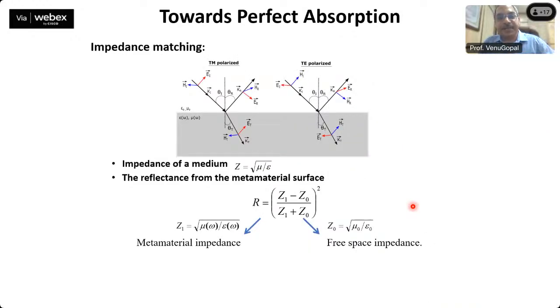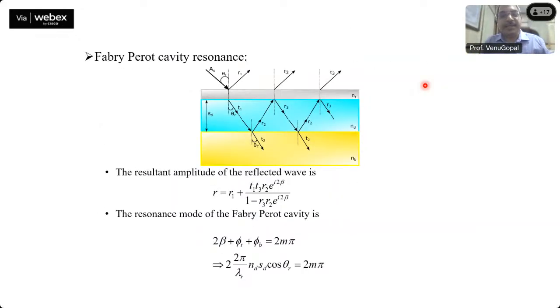I'll show one example of a perfect absorber. For different applications, sometimes we need 100% of the light to be absorbed within a few nanometer thick active or lossy absorbing material. For example, it can be 10 nanometer silicon, or 3-4 nanometer silicon, or germanium, or some other material with a small absorption coefficient. One of the first things to do is to reduce the loss because of the reflection, which means we need to couple the entire incident light into this active medium, or get impedance matching. For that, the reflection has to be suppressed, and for that the impedance of the top layer, for example,